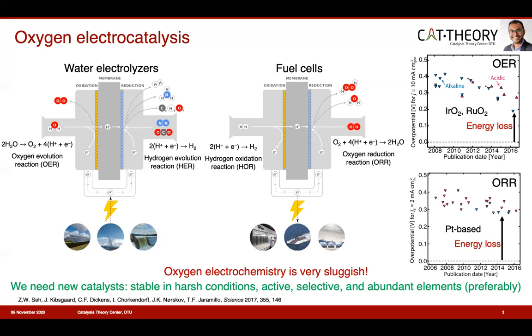conditions. So to date, the best known catalysts for OER in acidic solution are iridium oxide and ruthenium oxide and platinum for ORR. However, these catalysts have overpotentials of close to 0.4 volt. And most importantly, the high cost and the scarcity of these precious metals and the oxides hinders their commercial viability.